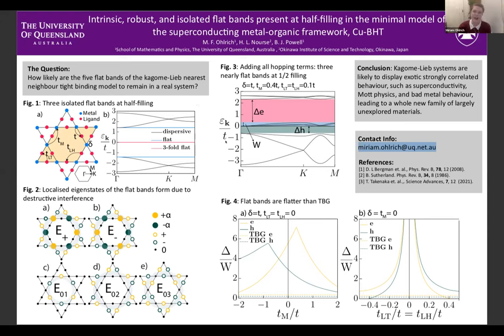There we go. Okay, so hi, I'm Miriam, and I'm going to be telling you about the Kagome-Lieb lattice, which is a Kagome lattice, but with an extra site added at the midpoint of each bond, in the same way the Lieb lattice is constructed from the square lattice. It's ubiquitous in metal organic frameworks, and it's a simple model of the recently discovered metal organic superconductor, CuBHT. We found using a tight binding model that this model has 5 flat bands. And our aim was to understand why these flat bands are present and to see whether these bands would survive in a real material that breaks the assumptions of this simple model.